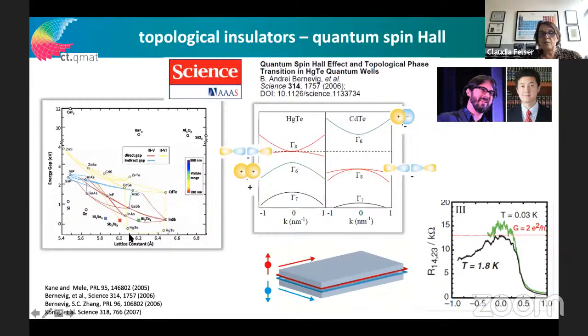If you go to the heavier element with band inversion, mercury telluride, you have this band inversion. This was the first realization of the quantum spin Hall effect. But the band inversion leads also to a problem: mercury telluride itself is not a semiconductor. From semiconductor industry, we know that if we build this quantum well structure with thin films of cadmium telluride and mercury telluride, we get the quantum spin Hall effect—a two-dimensional version of the three-dimensional topological insulator, with spin polarized currents at the edges.